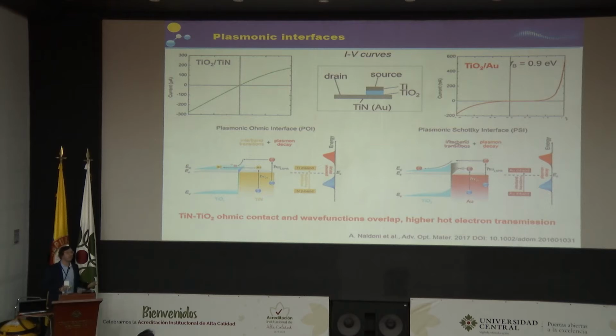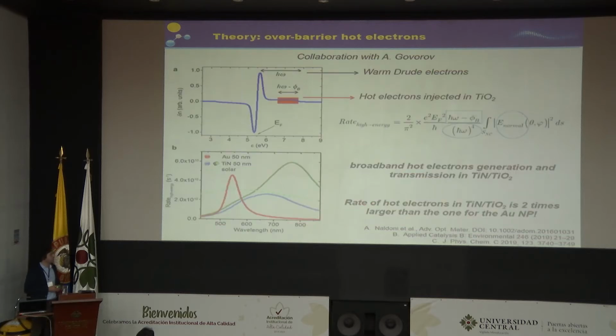So of course, the barrier from one side is important because it helps to divide the charges, so to keep the electrons on the semiconductor and the holes in the metals. But on the other side, when we are talking about a photoelectrochemical device, we can play a bit with the bias that we apply to these diodes, and so the possibility to have lower barriers really helps to have much higher hot electrons going from the metals to the semiconductor. And indeed, we did some calculation in collaboration with Sasha Govorov, which calculates the amount of hot electrons going from the metals to the semiconductor.